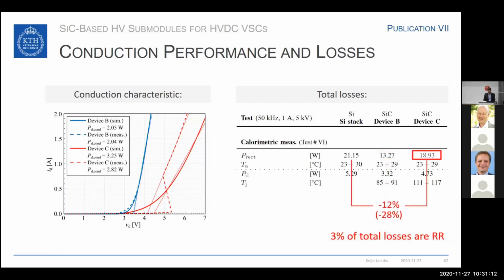Then we have the switching optimized device. Here we have losses of 19 watts. And you can see this is just a reduction of 12%, or 28% if you make a more fair comparison. Interesting to see in this case is that only 3% of the losses are reverse recovery losses. This means that this device would enable our circuit to operate at much higher switching frequencies. And this would enable us to reduce the passive components, such as capacitor and transformer, leading to a more optimized design of the converter.